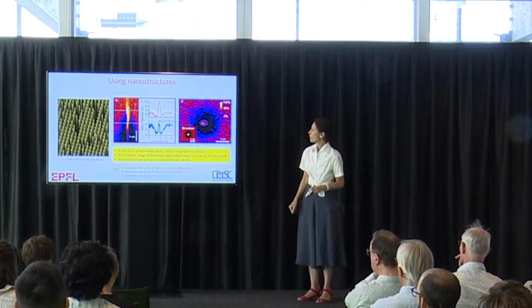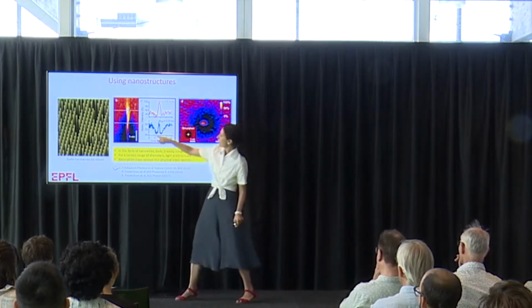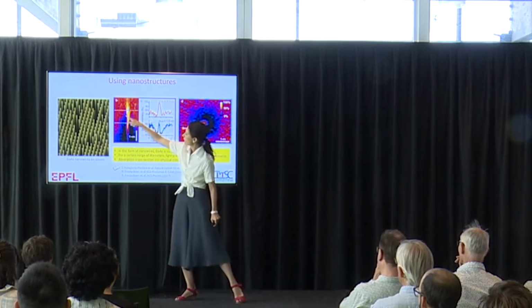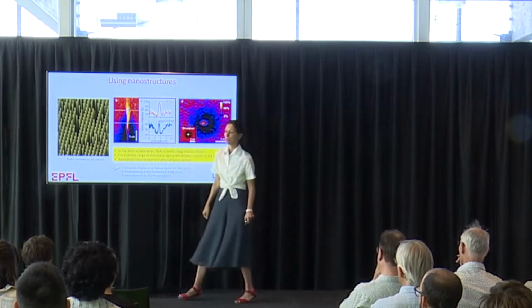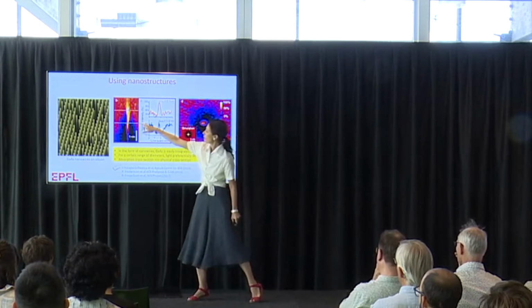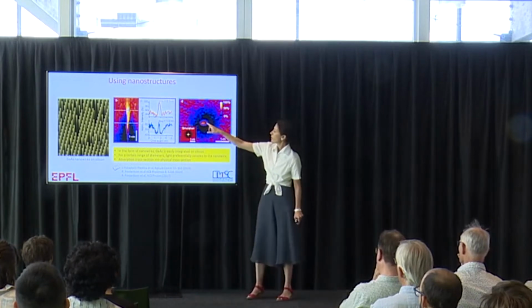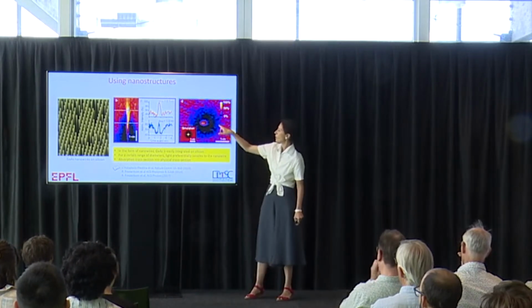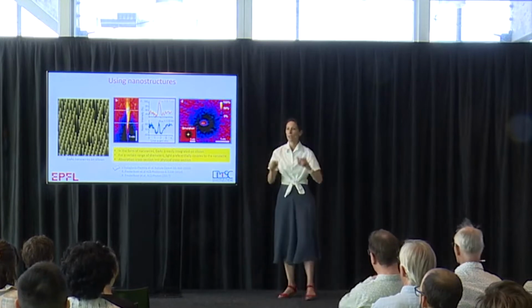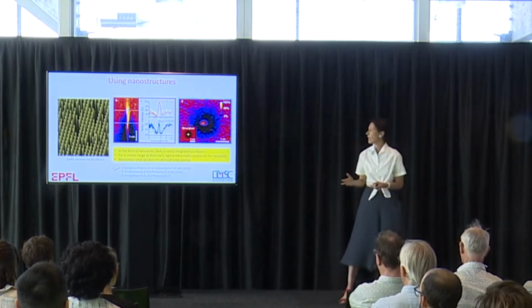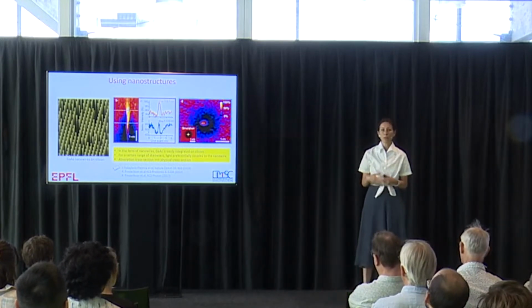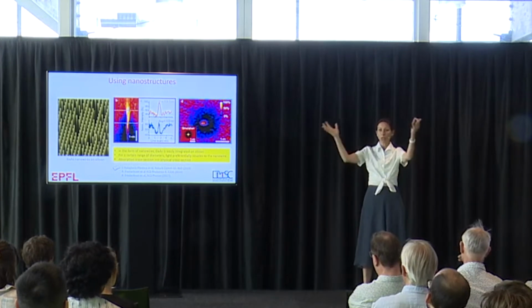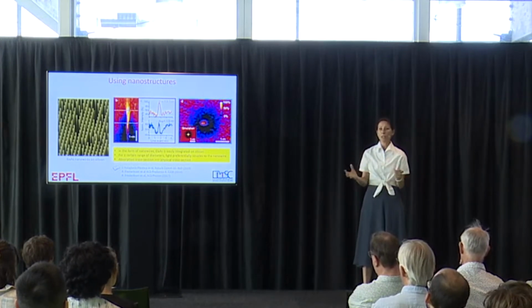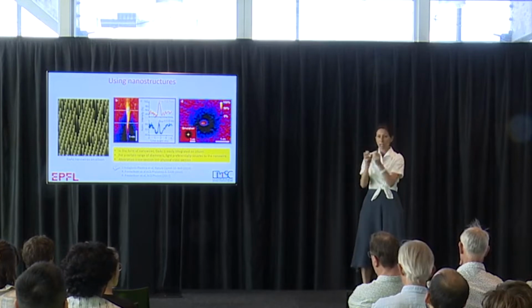And what you also see is that there is some light that disappears around the nanowire. So it's like creating a shadow of photons that have disappeared. If we do a cut here, we will see the leaky modes in the middle and a shadow that has developed around. So the photons have disappeared. What happens is that these leaky modes have a very good coupling to the wire, so you have very good photonic coupling to the wire, and this in fact makes you suck all this light inside.